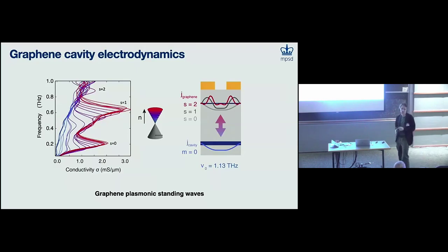So, Jim, since you mentioned single photon generation, what would be the source of nonlinearity? For generation, not sure yet. The detection is easier because you have these superconducting nanowires that people bias to the edge of critical current. Then a single photon creates runaway heating, and you get a resistance spike in the superconductor. That will be a direction. Have they done this at terahertz frequency? Not in terahertz. It's been done in the IR.